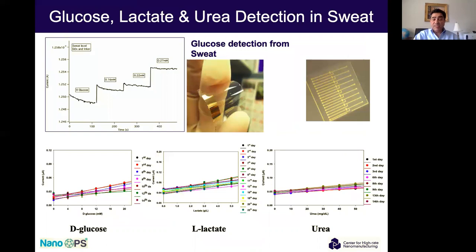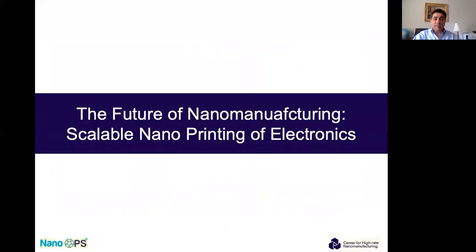We also use the same sensor platform, except this looks at the increase in current, because for glucose detection and lactate detection from sweat, the interaction between glucose oxidase and glucose, or lactate oxidase and lactate, produces electrons. So as a result, your current goes up, not down. And so you need conductive nanotubes here. So this works also with sweat, and this was tried actually by very large companies, and people have used it while exercising and so forth. And it maps very well with the concentration in sweat.